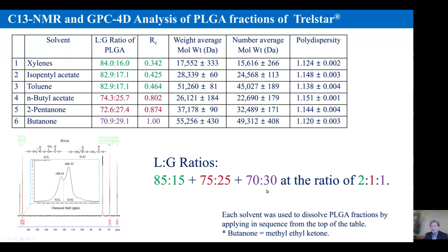This is the beginning of the formulation, because I don't think that any standard manufacturer would purchase anything other than 85-15, because as far as I know, no manufacturer makes 83-17 or 73-27, etc. So the bottom line is that these are raw materials, but what we need to do is characterize the PLGA composition of the final formulation. This is why FDA set out to develop a number of different assay and analytical tools to isolate the PLGAs and understand which PLGAs they are in the final formulation.